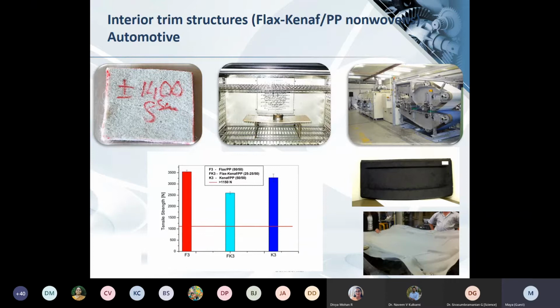So this just shows the tensile results of the nonwovens that we developed. The requirement was that the tensile strength should be greater than 1,100 newtons. And as you can see, all of the nonwovens that we developed are meeting the requirements. Examples of secondary structures or interior trim structures are the parcel trays, the door liners, the side liners, and so on.